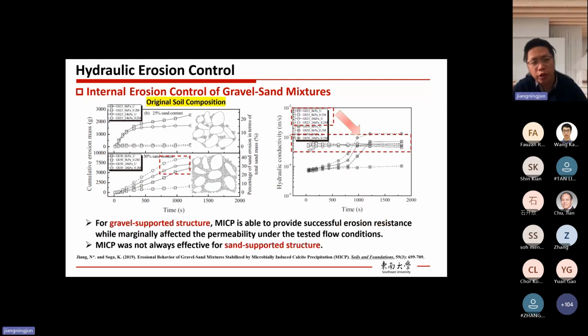In addition to the cementation solution concentration, the original soil composition is also a quite key factor. So here we investigate two cases. One is with 25% sand, the other is with 50% sand. For 25% sand, this is basically a gravel supported structure. It means the skeleton is mostly gravel and the sand particles are loosely distributed within pores. For the 50% sand content case, this is basically a sand supported structure. It means that the skeleton is formed by sand instead of gravel.